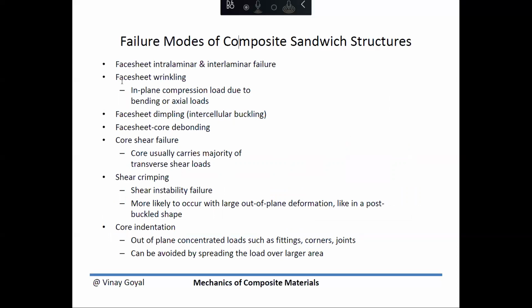And for face sheet, you want to really track intralaminar, meaning in the ply in-plane directions, and interlaminar failures. You also have face sheet wrinkling, which depends on the in-plane compression loads. You also want to take a look at, for core shear failure, the transverse shear loads in the core. And then for shear crimping, you want to look at the potential for large out-of-plane deformation due to buckling. You could have core indentation issues as well that could cause core to crush, such as an impact damage event.